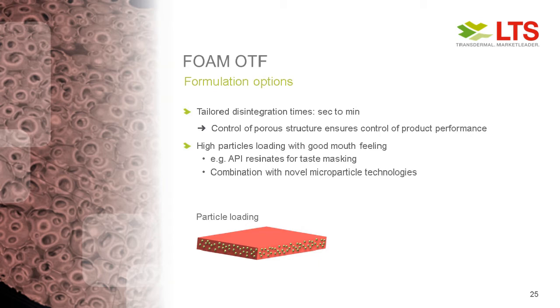So what we can do with the foam formulations, the options which we're having, the disintegration time can be tailored from seconds up to several minutes. And this can be done, of course, by the polymers, the polymer blends, but also by the control of the pore structure. And by that, we can ensure really a constant product performance.